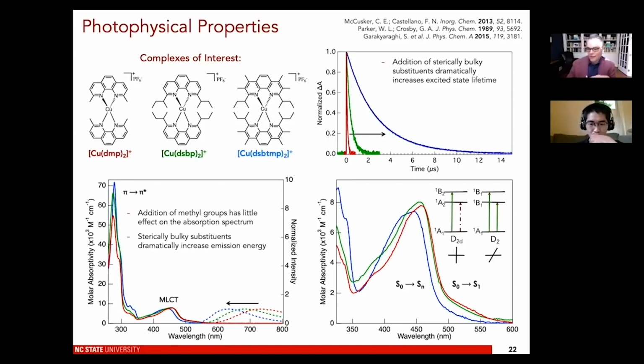And the result of that is you get a bigger Stokes shift, and then the energy gap law tells you that that's more favorable for non-radiative decay to the ground state. So the DMP compound has under 100 nanosecond lifetime.